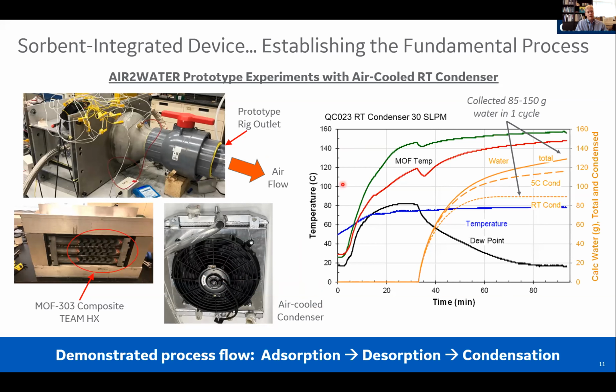Over on this plot on the right, you can see temperature in degrees Celsius over on the y-axis, and the time shown over on the x-axis. You can see all these thermocouples here. We can actually get temperatures at around 12 to 16 different parts of the entire system. So you can see the temperature rising to drive off that water. We can get the temperature of the actual water that is being desorbed coming out. And one of the keys is really driving high dew point, because the higher dew point that we drive, the greater amount of water we can collect.